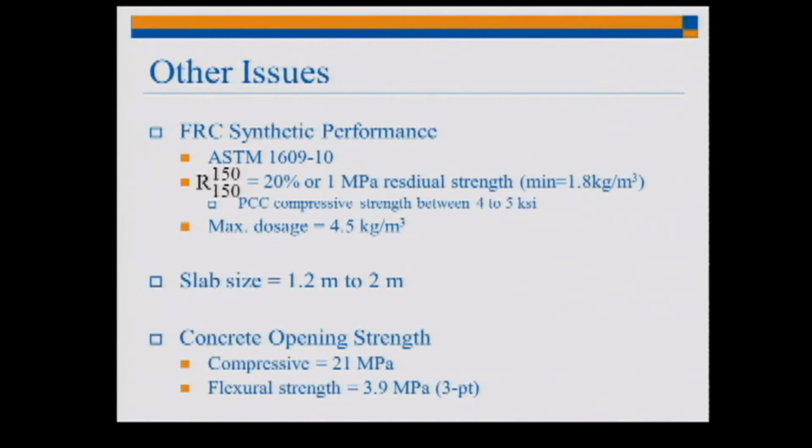So if you're doing a parking lot, you'd have to use 1.8 kilograms per cubic meter. If you're doing another type of road, you don't want to exceed about 4.5 kilograms per cubic meter. Slab sizes vary between these values, so we don't get much above 2 meters ever.